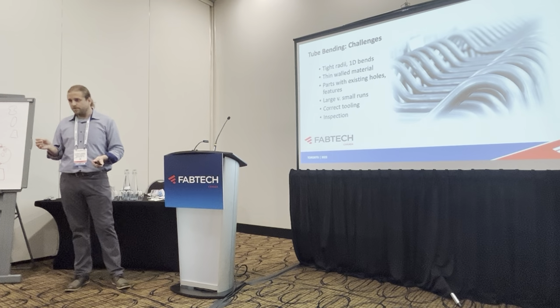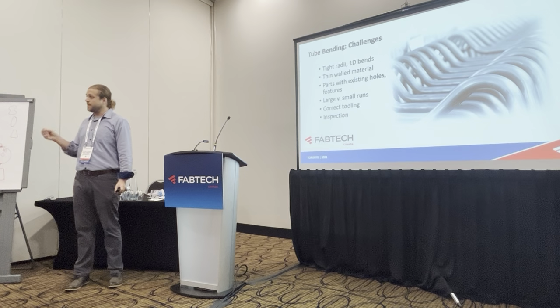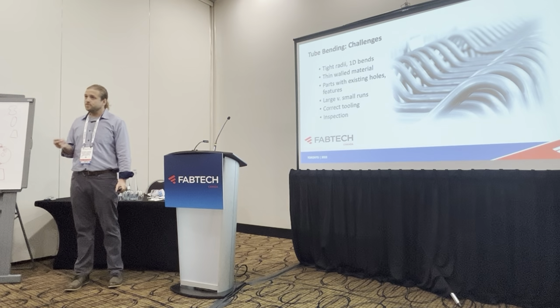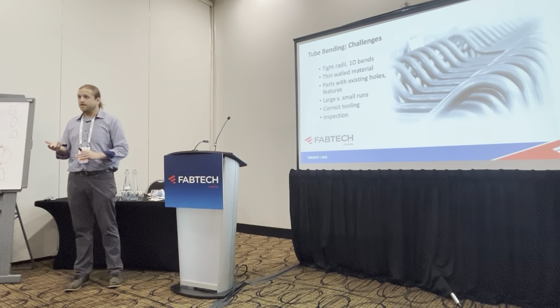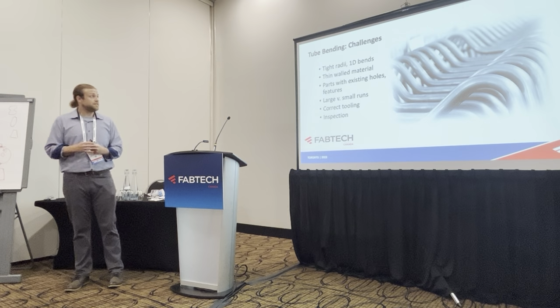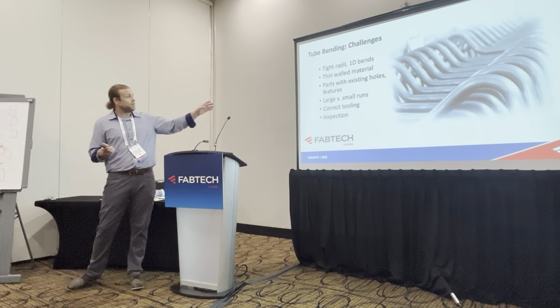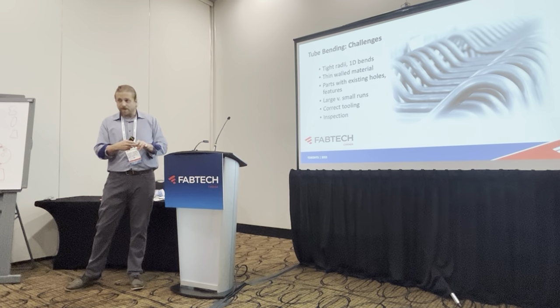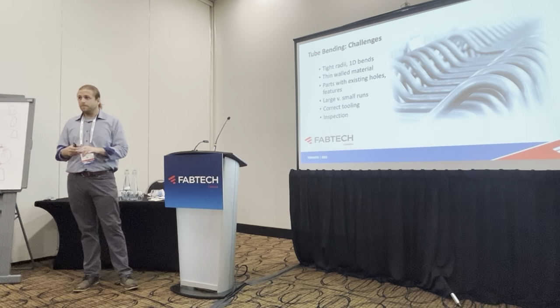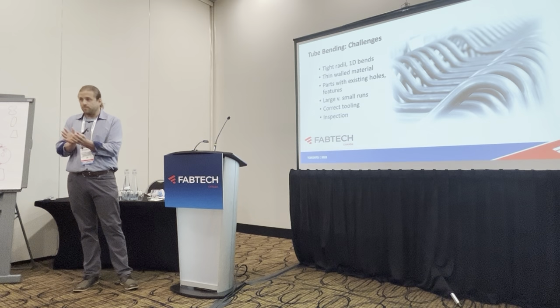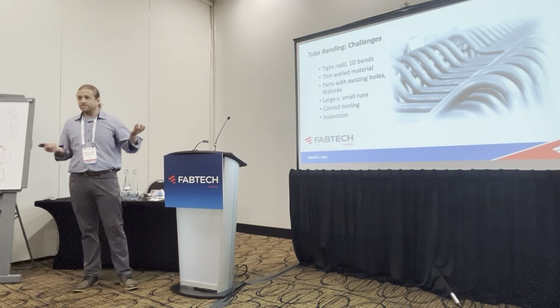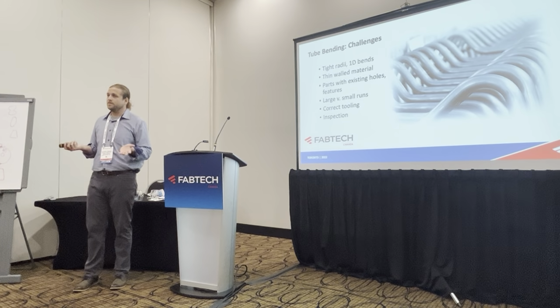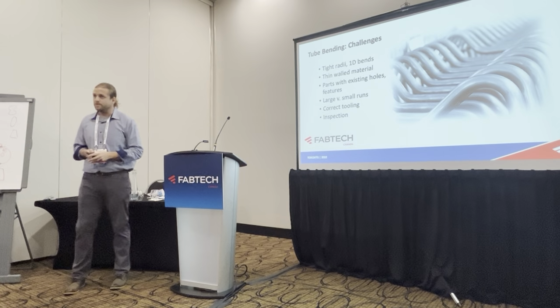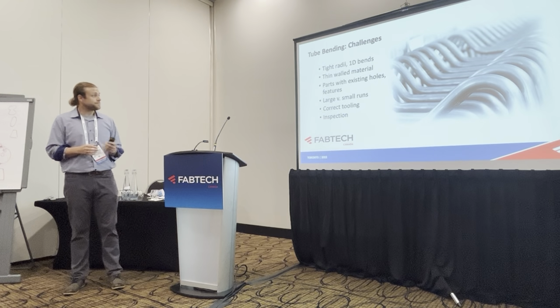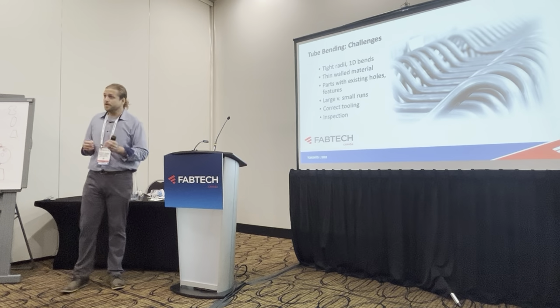So general rule is 3 times the diameter away from the tangent point of the bend to eliminate cracks, deformation, things such as that. So if you put a hole right near the bend, it's most likely going to either pull and create a cat eye or crack, or it could actually crush. And those are things that you obviously don't want, because now the hole is unusable to the customer and it's out of tolerance.